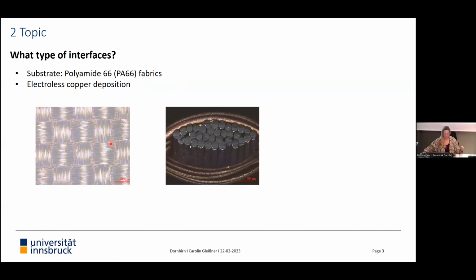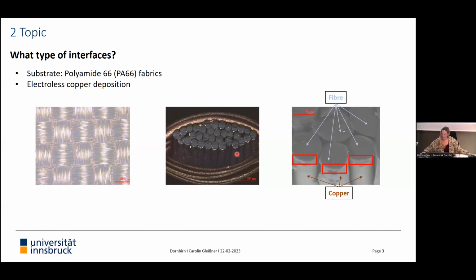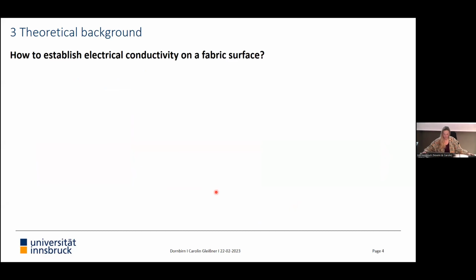If we look at the cross section of this metallized fabric, you can see these fibers that are coated with the metal, and you already see what the topic is. I'm looking at these copper polyamide interfaces. In a scanning electron microscope, you see this even better. So you have the fibers here, you have the copper coating here, and what I'm looking at is these PA66 copper interfaces. So in this specific type, how do I establish the electrical conductivity on the fabric?